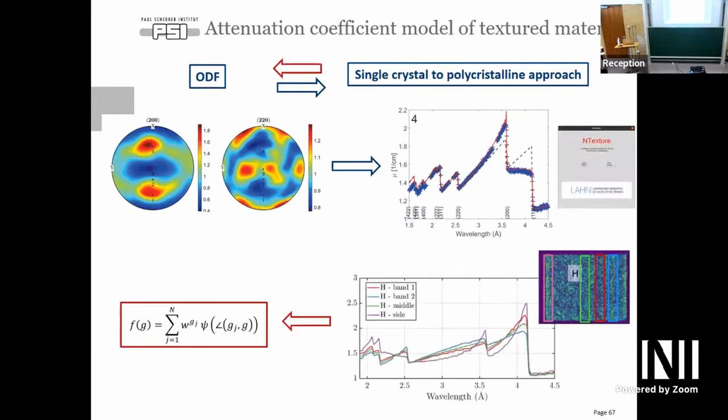But now the problem is from this particular tomographic reconstruction. This is the same sample that we measured here. If we took just the central region of the sample, everything was fine, and the central region of the sample is what I showed you before. However, if we move the region of interest a little and measure the transmission here, or even at the surface, the transmission looks completely different. The pattern looks completely different. This means that we have a texture gradient in this direction.